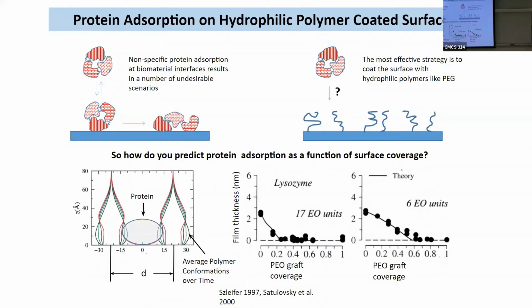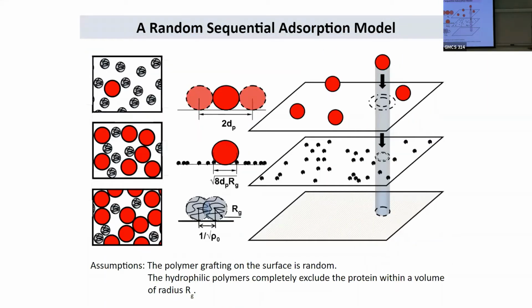And so we're like, okay, let's think about the problem from our own science. So he said, okay, you have these hydrophilic polymers. They love to retain water, right? The polymer is sort of fluctuating. And so it has a certain excluded volume, where it traps the water. And that has to do with the radius of gyration of this polymer, which is when the polymer is thermally fluctuating, it can move around. And there is sort of an end-to-end distance between the two, one end tethered to the surface and the free end of the polymer, right?